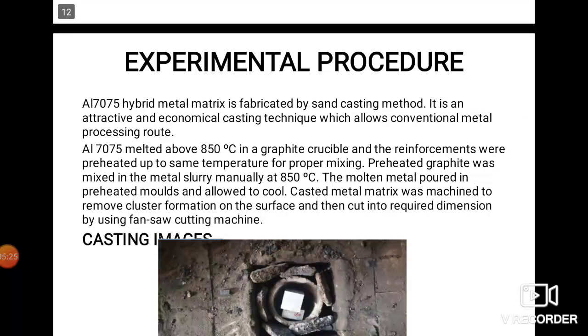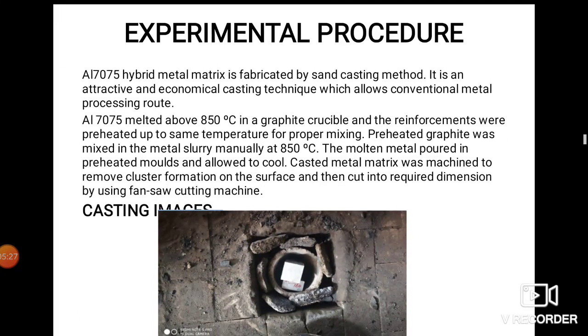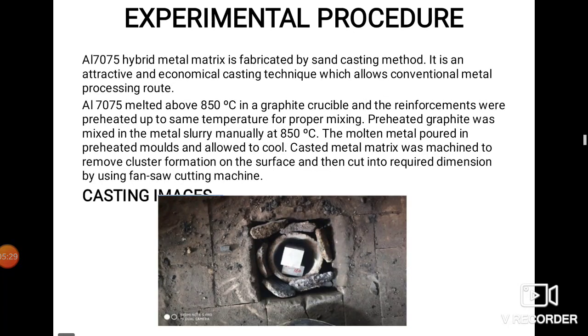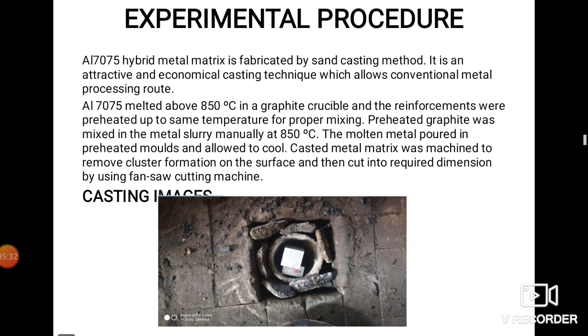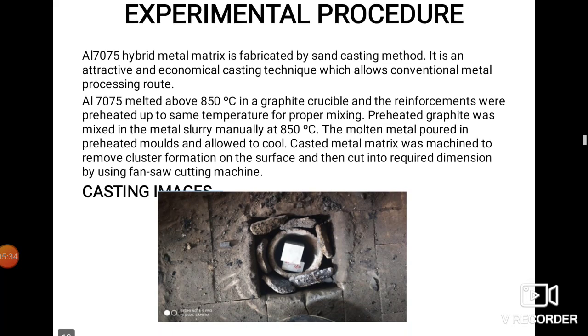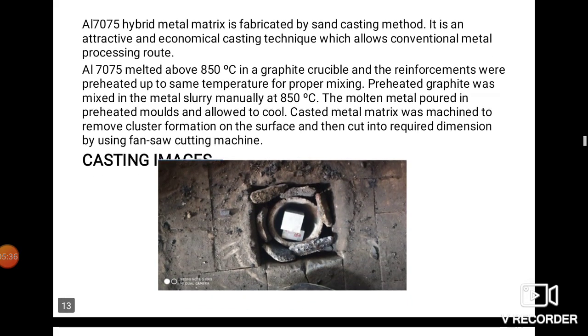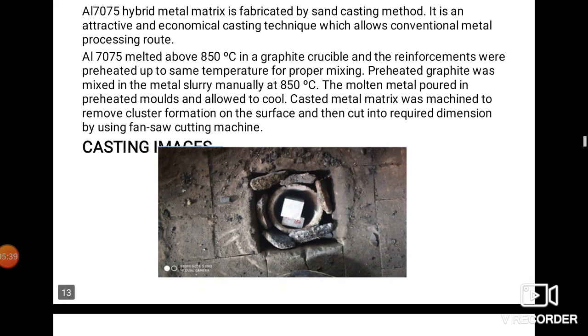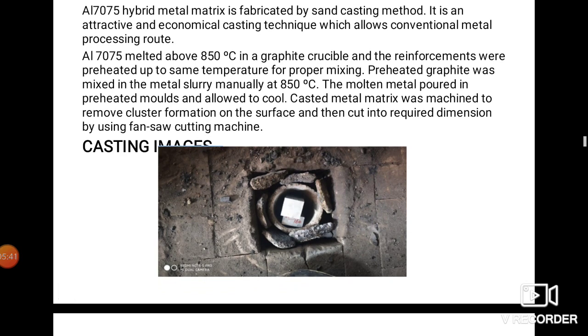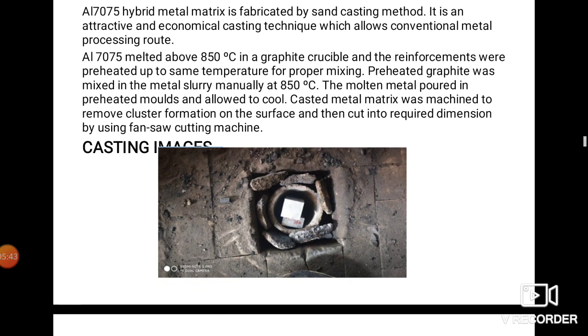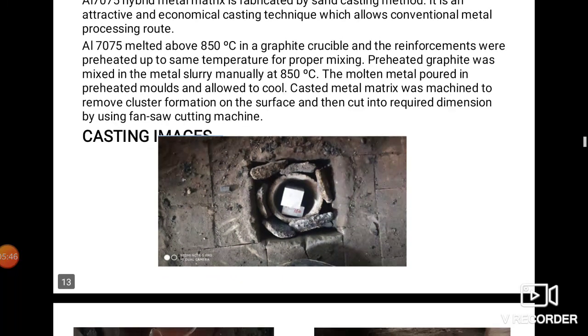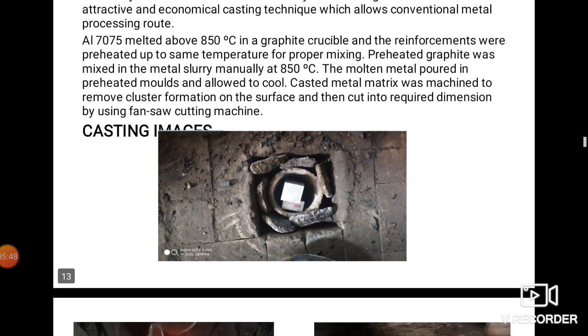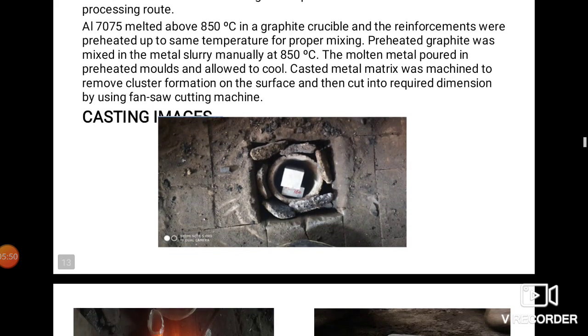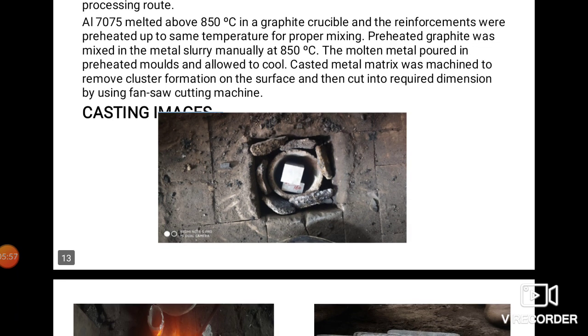Next, the experimental procedure. Aluminium 7075 hybrid metal matrix is fabricated by sand casting method. It is an attractive, economical casting technique. That's why we have chosen it. Aluminium 7075 is melted up to 850 degrees in a graphite crucible and the reinforcement was preheated to the same temperature. Preheated graphite was mixed in the metal slurry manually at 850 degrees. Here are the casting images.